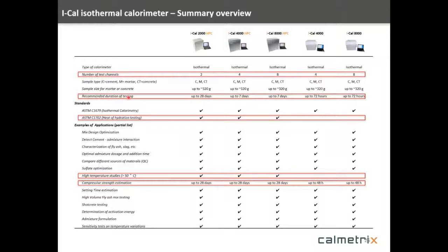Another area is how long you want to test for. All of our instruments, basically, there's really no limitations on how long you test, but from a practical standpoint, on these types of experiments, typically if you really want to run up to 28 days, we recommend our highest performance instrument, the iCal 2000 HPC. This really relates to the fact that the HPC has the absolute best baseline, has very minimal crosstalk between sample channels, so it's really the highest performance of our instruments. So the recommended duration of testing is important. Whether you need to follow ASTM C1702 is important.